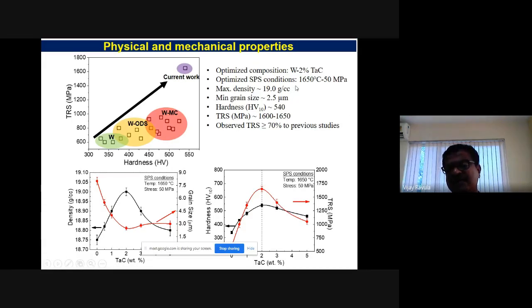Tantalum carbide is used, and we were able to get around 1600 to 1650, which is much higher. So we have done a lot of experiments and optimized the tantalum carbide content, what we need in terms of density to get a good density and good hardness. Then we made a lot of pieces and supplied them to DRDL, where the field trials are taking place. And this technology is ready for transfer. Industry is also interested in taking up this technology.